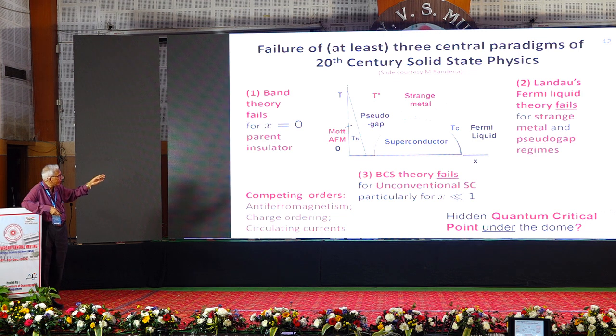and the antiferromagnetic transition comes down as you dope, and then you have this superconducting dome, and you have another phase which is called a pseudo gap phase, where there is not a gap, it's not an insulator, but the density of states kind of has a dip near the Fermi level. That's why it's called a pseudo gap. And above the superconductor, there's something called a strange metal, where the resistivity looks linear in temperature to very high temperatures. Nobody understands that. So we call it a strange metal. It's metallic, it has a resistivity, but it looks linear, and the mechanism is not due to phonons or anything, so we don't understand exactly why it's linear. And then rightmost, there's something that looks like conventional metals.